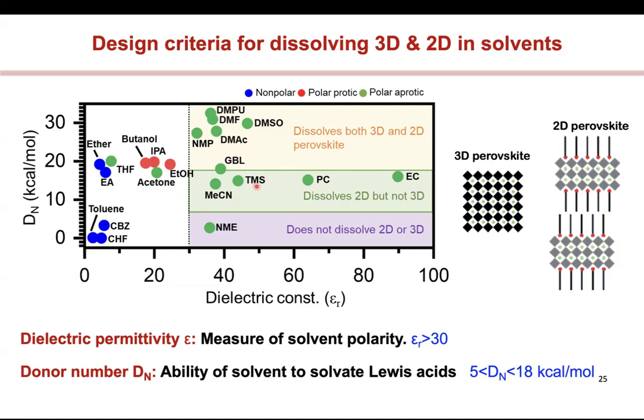Okay. And so this was quite interesting for us. And then, of course, there were some solvents, in this case, for example, NME, which does not dissolve both the 2D and the 3D. Everything just crashes out. Okay. And so we set out to do this, where we took acetonitrile, and using our memory seed method, we put everything inside, and we dissolved the 2D perovskite in this, right?